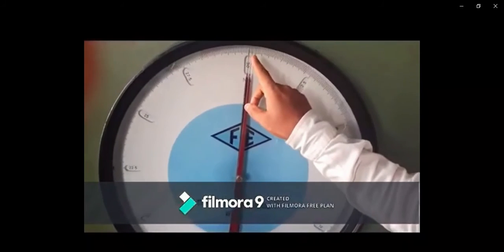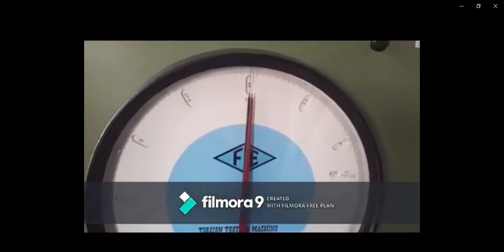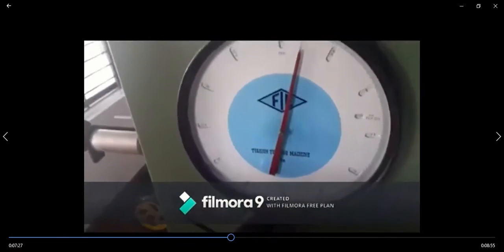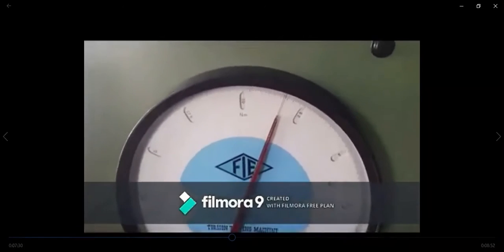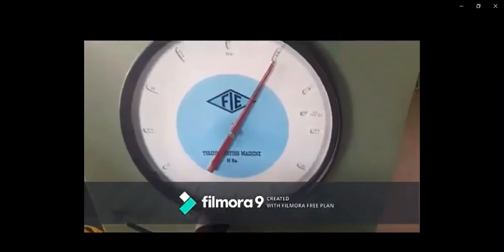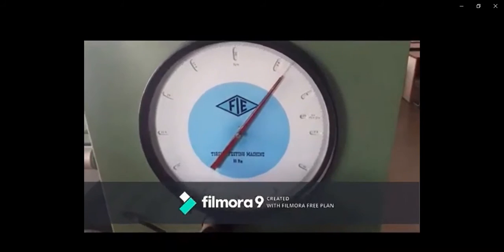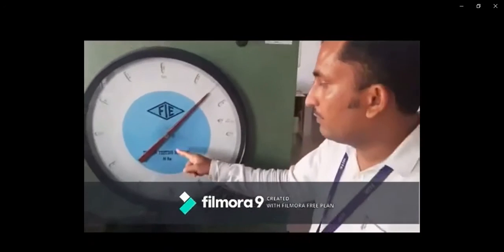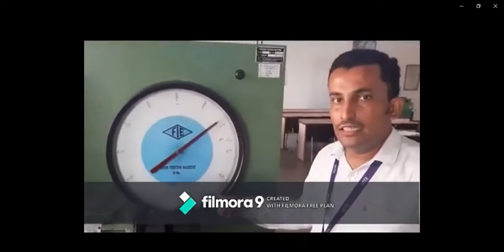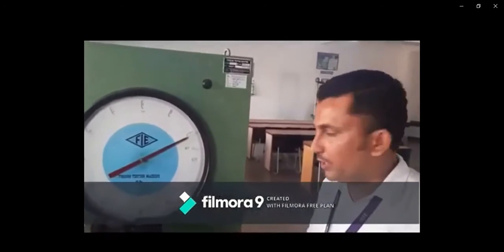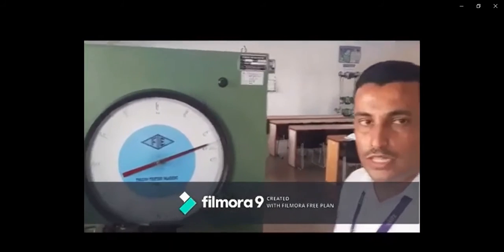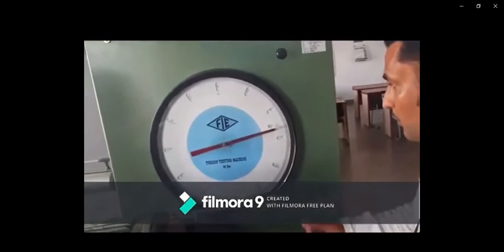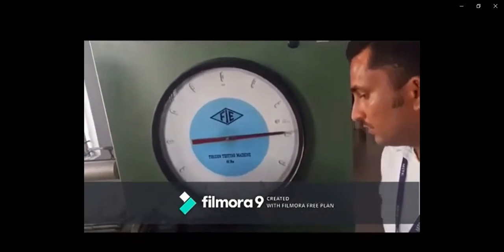Now the reading for 2 degree. Here we have 2 divisions. Each division carries 0.05. 2 divisions means it is 0.1 Newton meter. So like that, for every 2-degree reading you need to consider the torque. Once it reaches the yield point, the black needle will come back and the red needle will be stopped there. That reading will be taken as the yield strength or yield torsion at yield point. So that is very, very important for the calculation purpose. Keep on rotating and take the reading for every 2 degrees.